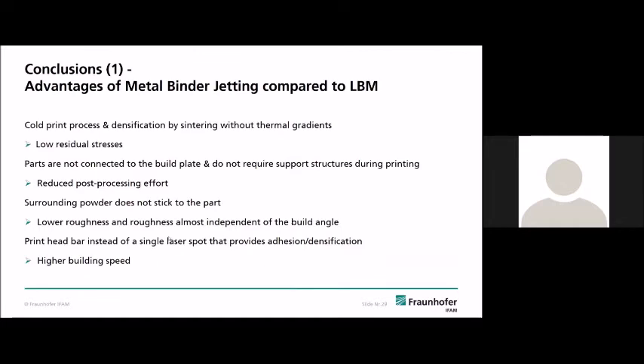with binder jetting, in comparison with the beam-based processes, we have a cold printing process, which ends with very low residual stresses, so no cracks from the printing step in this process chain. We have no connection to any build platform and not that much support structures to be removed. The surrounding powder can be recycled, so the powder which is not glued together. We have a quite low roughness, and the roughness is almost independent of the build angle. So the roughness on the top of the part is comparable to that at the side of the part.